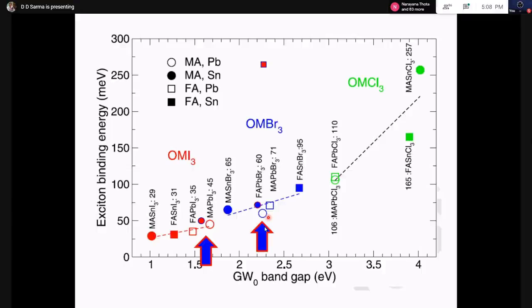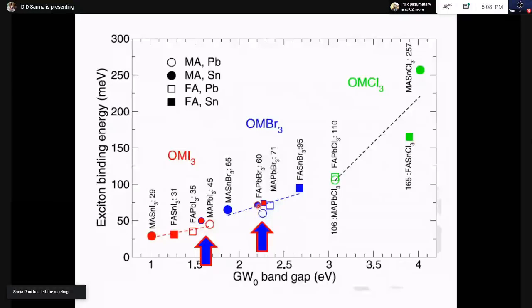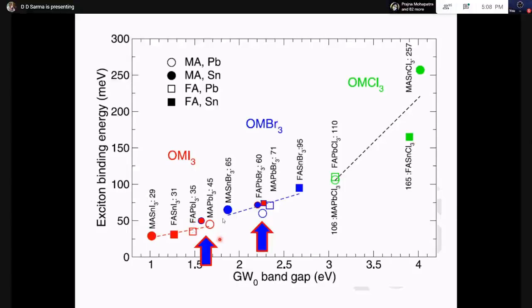And if I put our experimental data on this, you can see experimental data is here, very close to the calculated value. And here, these two are very close to the calculated value. This experiment corresponds to this value. So there's a very good agreement and consistent set of excitonic data that we have got. And that brings me to the end of my talk.